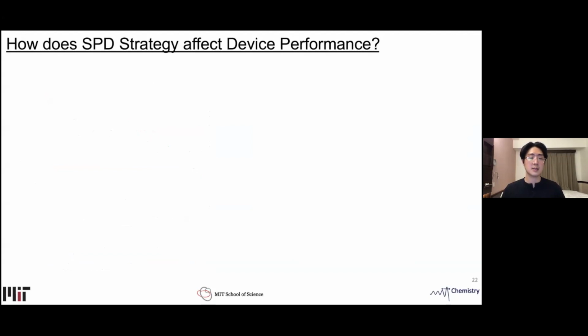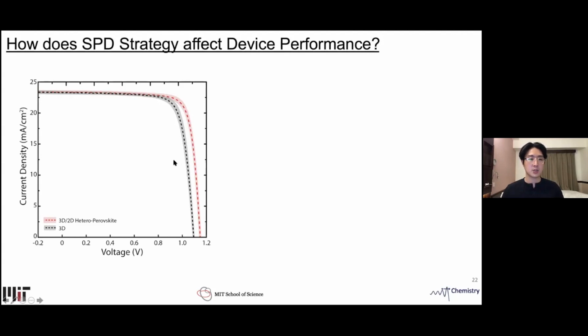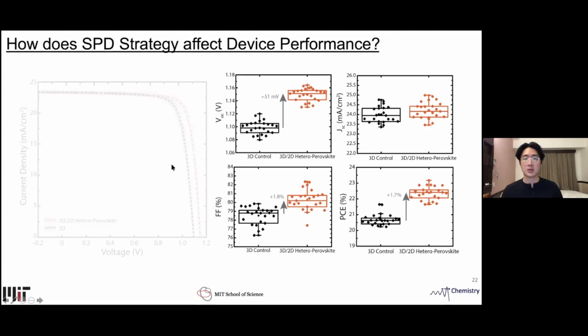So how does the 2D perovskite passivation using the SPD strategy affect device performance? On the left, I'm showing a JV curve of the 3D control and the 3D heterostructure, where the dotted line is the average and the shaded area is the distribution. On the right, I'm showing device statistics of 4 metrics: VOC, JSC, fill factor, and power conversion efficiency.